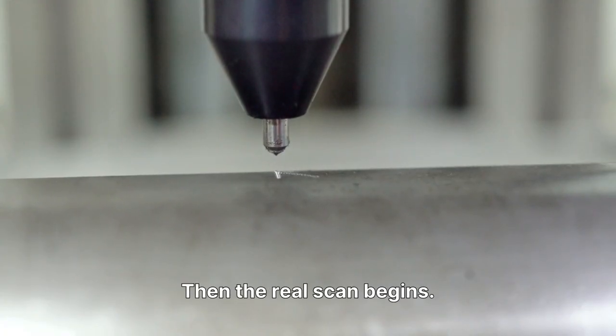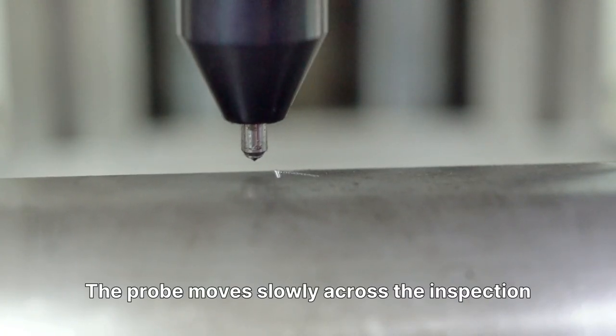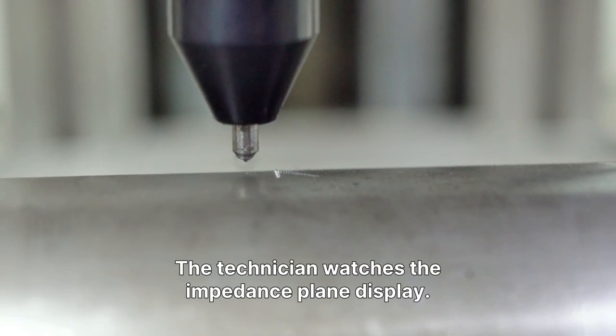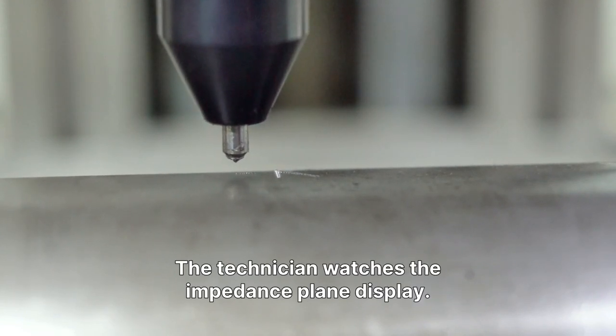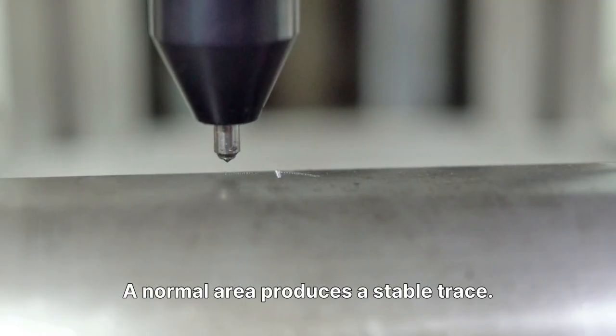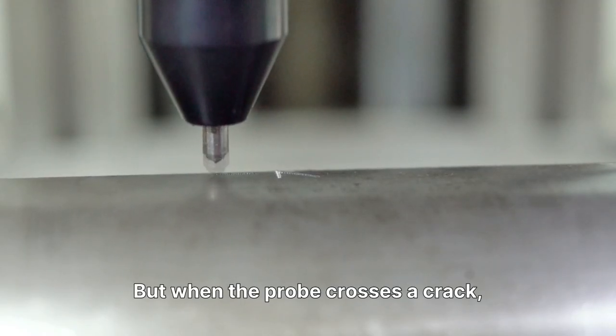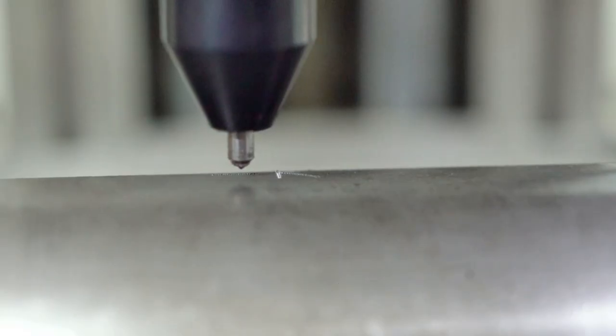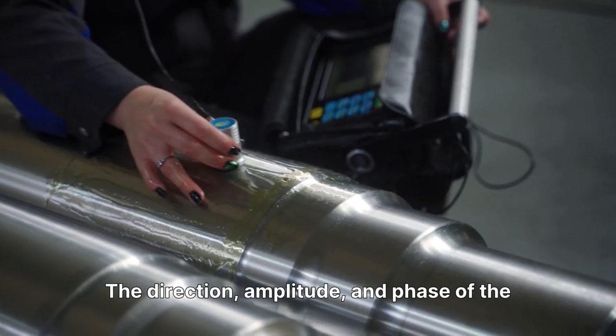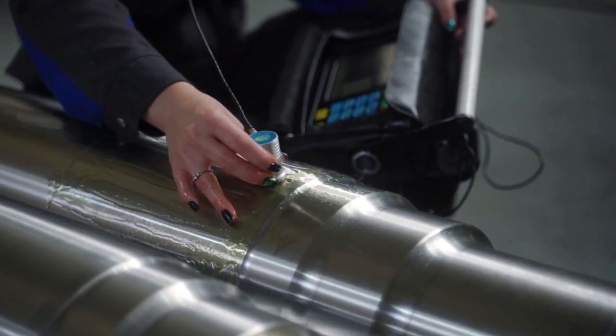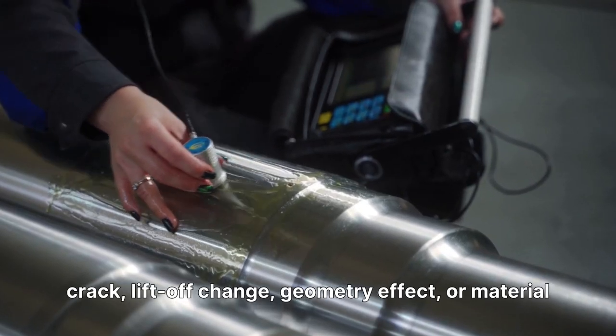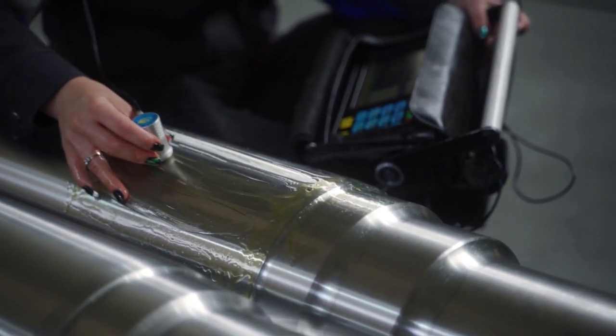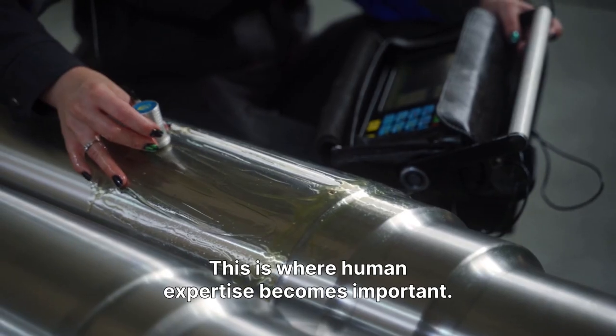Then the real scan begins. The probe moves slowly across the inspection surface. The technician watches the impedance plane display. A normal area produces a stable trace, but when the probe crosses a crack, the signal shifts. The direction, amplitude, and phase of the signal help identify whether it is a crack, lift-off change, geometry effect, or material variation. This is where human expertise becomes important.